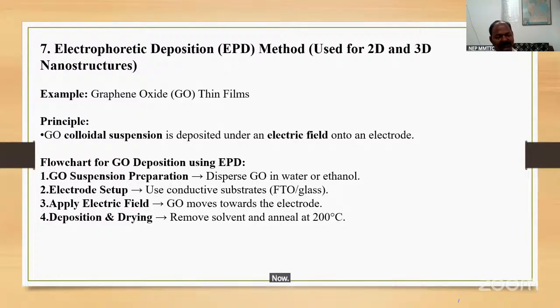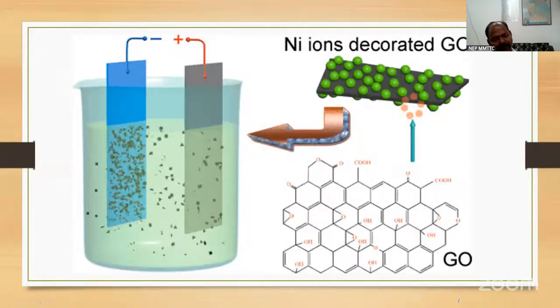Now, GO suspension preparation: disperse GO in water or ethanol. Electrode setup: use conductive substrates such as FTO or glass. Now we have to apply the electric field. GO moves towards the electrode. Deposition and drying: remove solvent and anneal at 200 degrees Celsius. See, this is the pictorial diagram of this one, and how the material is deposited. Okay, this is the nickel ion decorated GO.